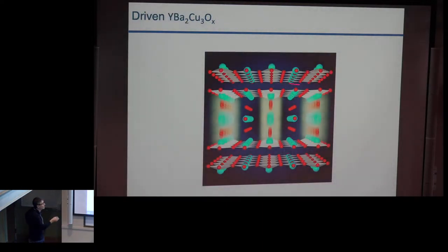Now, what we're going to do is an experiment in which this is YBCO, these are the superconducting planes. And what we want to do for our Floquet transducer is to modulate the position of this particular oxygen atom. So imagine the 2p orbitals of an oxygen atom that go in and out from the superconducting planes and hybridize or not hybridize depending on the distance. And so they allow you to effectively put your Floquet drive into the Hamiltonian.